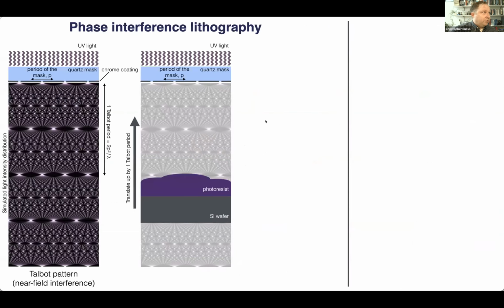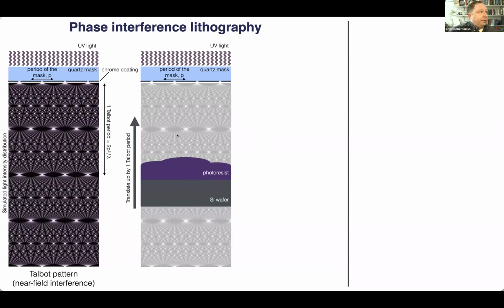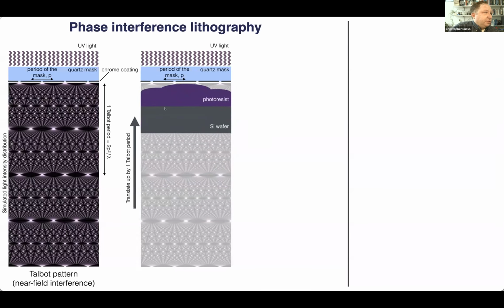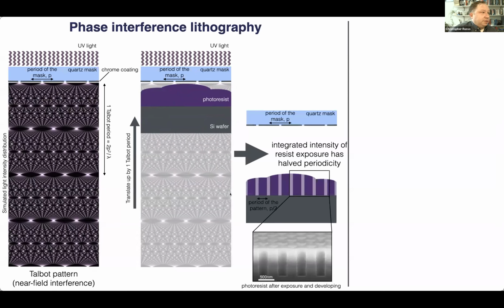So I'll just highlight two pieces of this lithography process that were somewhat unusual relative to standard wafer processing techniques. One of them was using phase interference lithography. To make holes smaller than the wavelength that you were using for your typical mask aligner system, that's not so easy to do, but there is this technique that uses phase interference lithography and a variable distance between the wafer and the mask to increase the effective resolution of the mask such that we could make 200 or 300 nanometer holes, even using a mask that had much less fine spacing than that. It's called Talbot interference lithography, which was developed for other things, but we took advantage of it here.